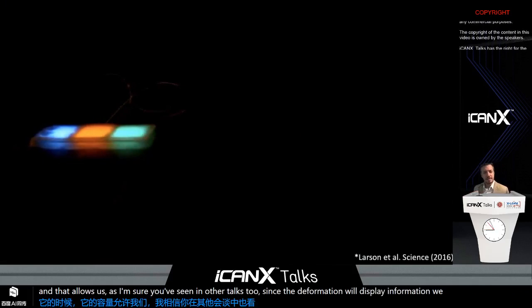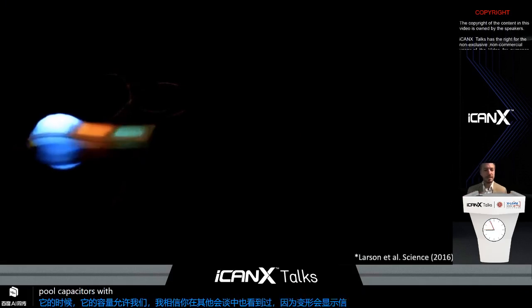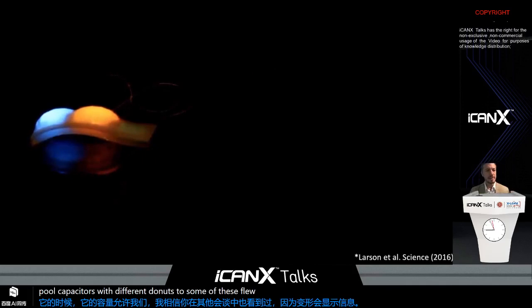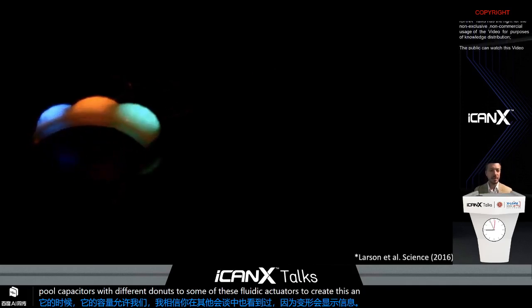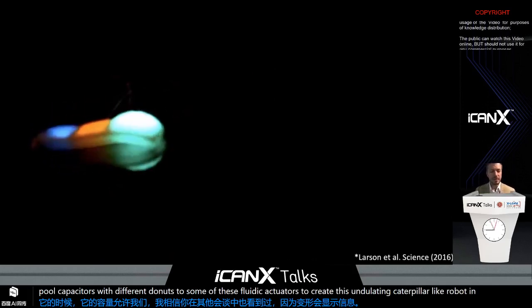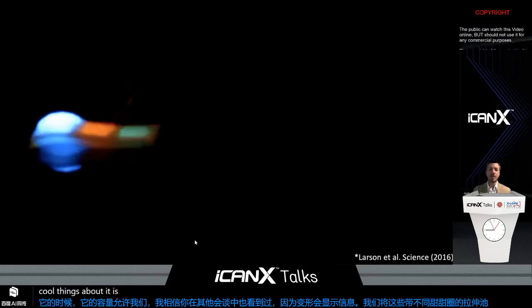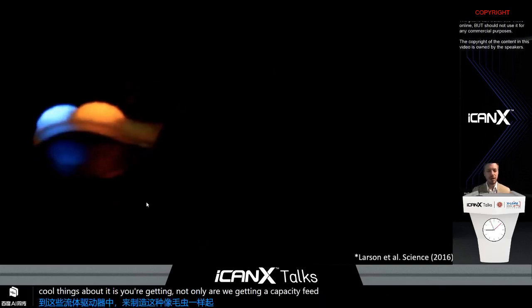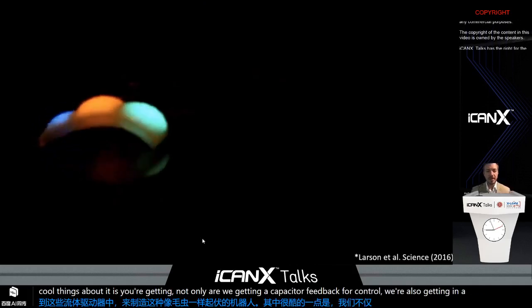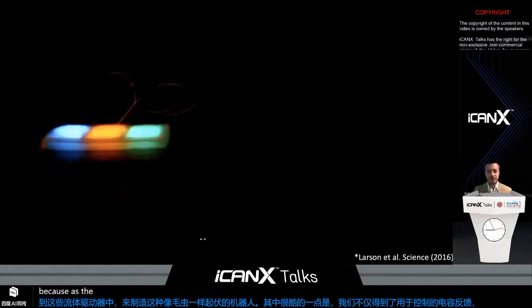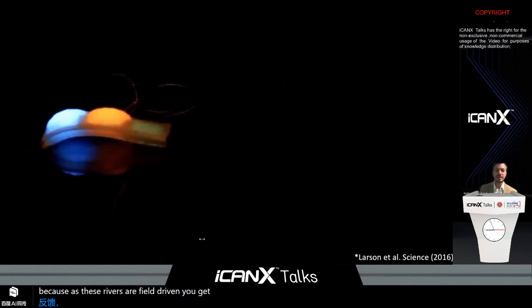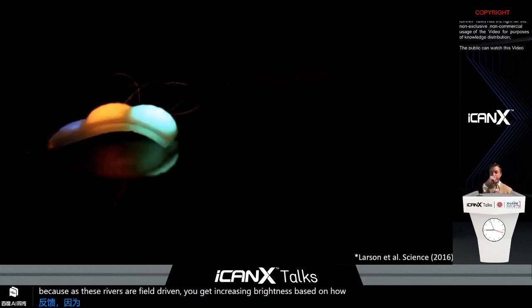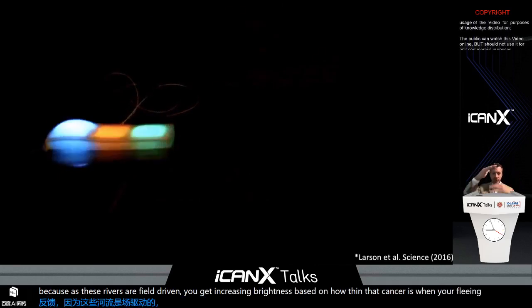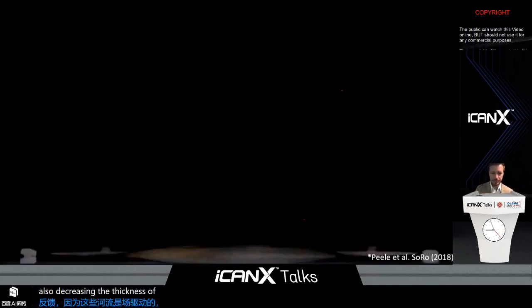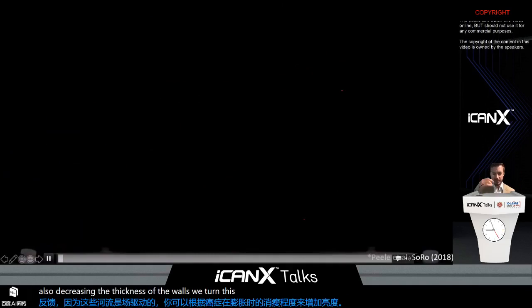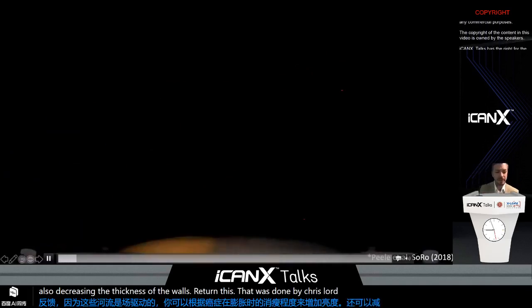We applied these stretchable capacitors with different dopants to some of these fluidic actuators to create this undulating caterpillar-like robot. And one of the cool things about it is that not only are we getting a capacitive feedback for control, we're also getting a visual feedback, because as these rubbers are field driven, you get an increase in brightness based on how thin that capacitor is. When you're inflating it, you're also decreasing the thickness of the walls. We turned this, and that was done by Chris Larson, Brian Peel, and Shuo Li, by the way.